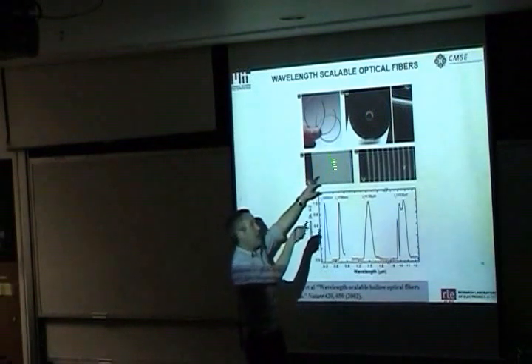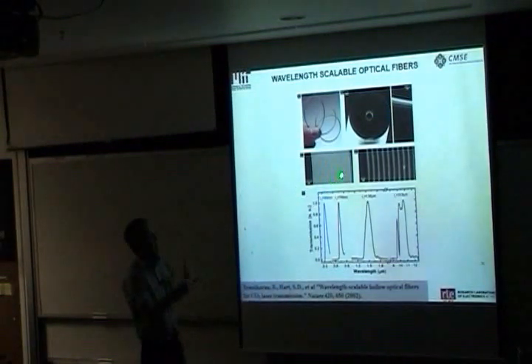So you see there's a hollow core here, and this ring over here, when taken up to large magnification, you can see has many layers. This is 250 nanometers, so each layer here actually is less than 100 nanometers. And the nice thing here is that these fibers guide light by virtue of the structure.